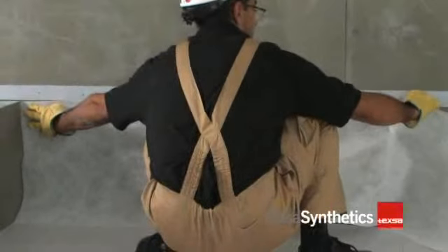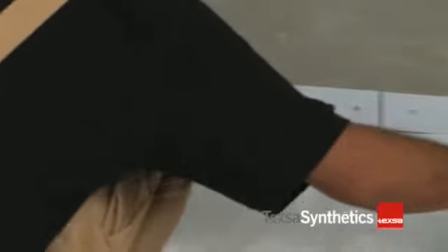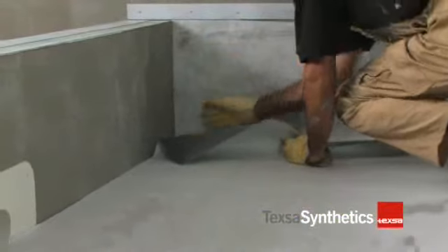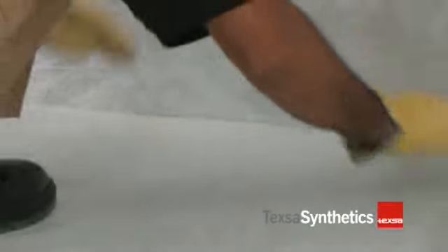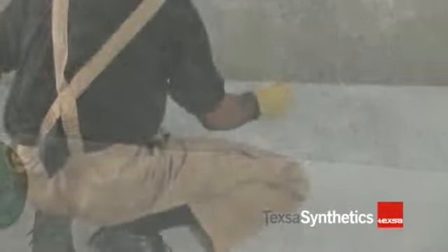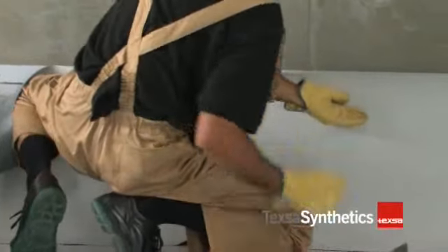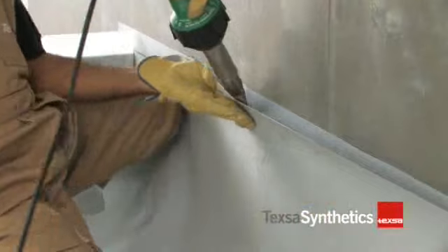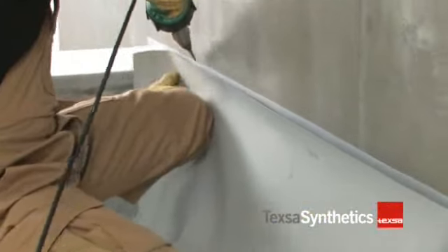Edge flashing. Wall flashing. When meeting a wall, the waterproofing must extend 20 centimeters above the finished deck. Place a geotextile layer to protect the membrane. The membrane can also be adhered to the support structure with VINITEX bonding adhesive, especially if the area to be covered is quite high. Spot weld the top edge to a laminated termination bar.